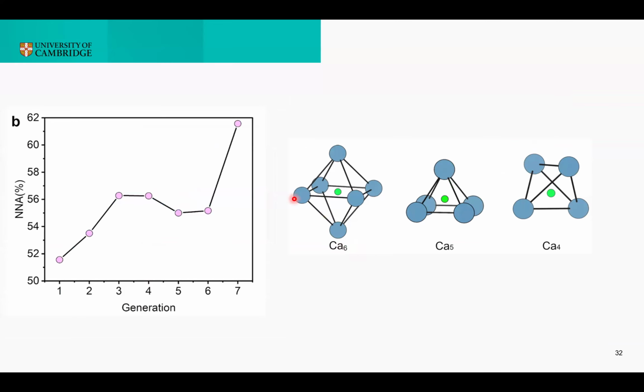In this case, the answer seems to be yes. On the left here, I'm showing the percentage of phases possessing a non-nuclear attractor against the generation in these crystal structure predictions. And you can see that the percentage increases, meaning that the multi-objective search tends to select those phases that are more probable to be an electride.